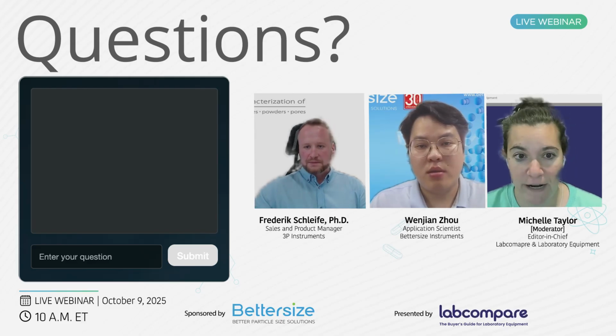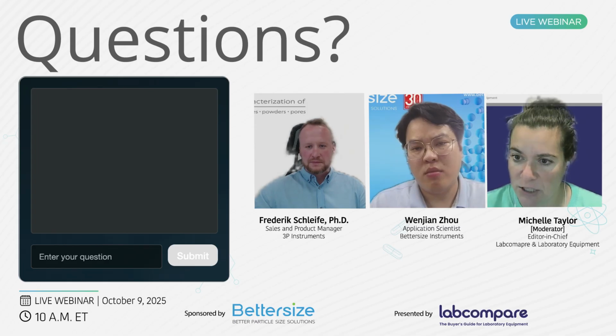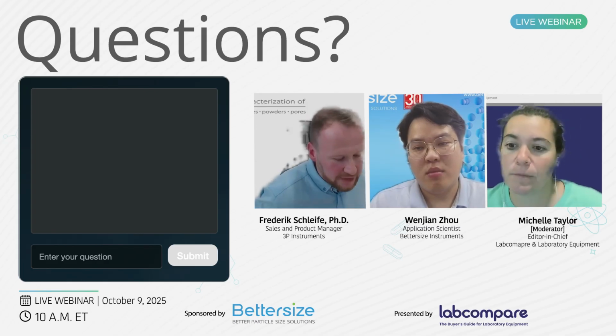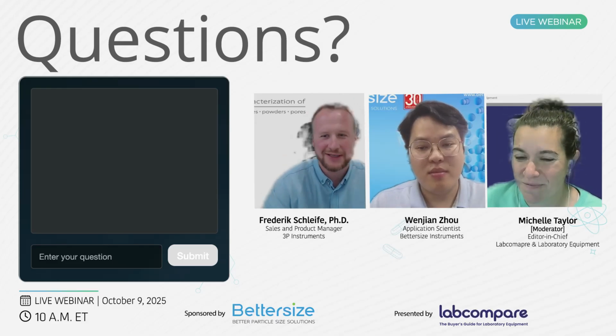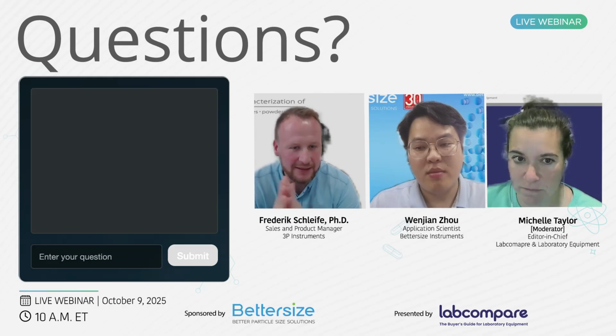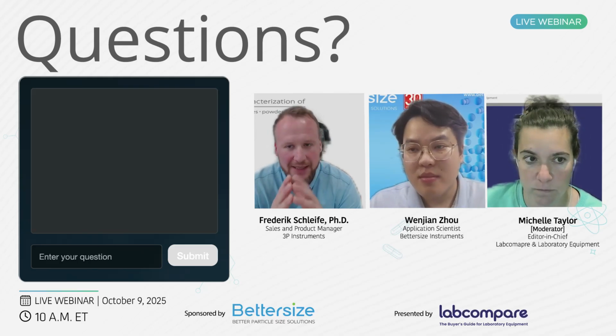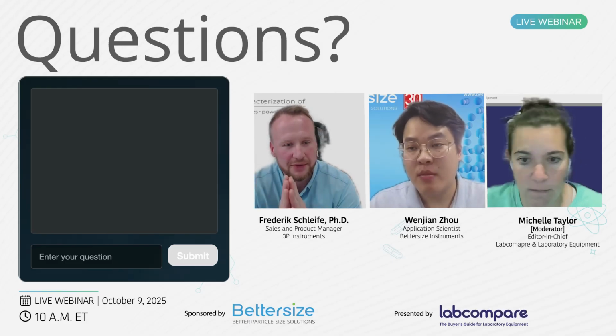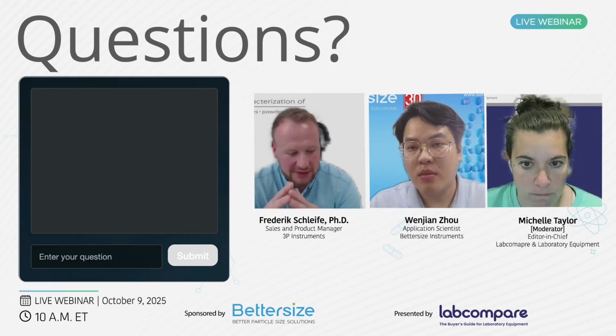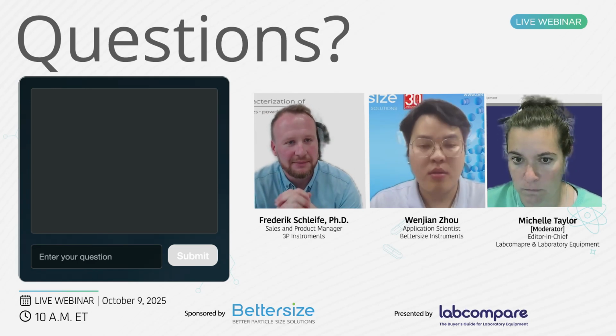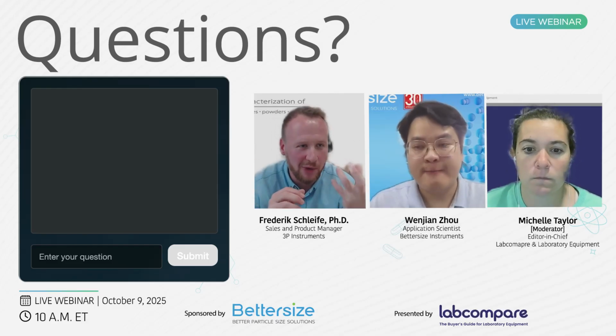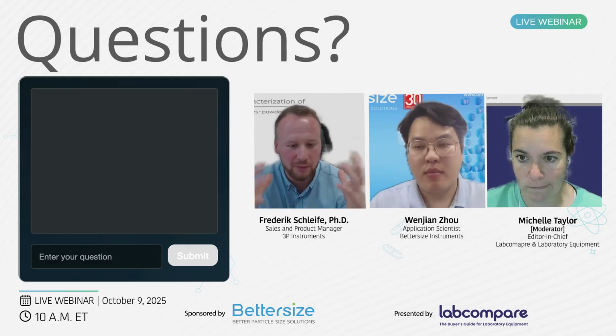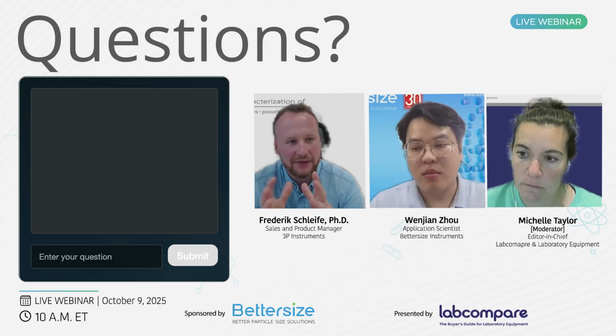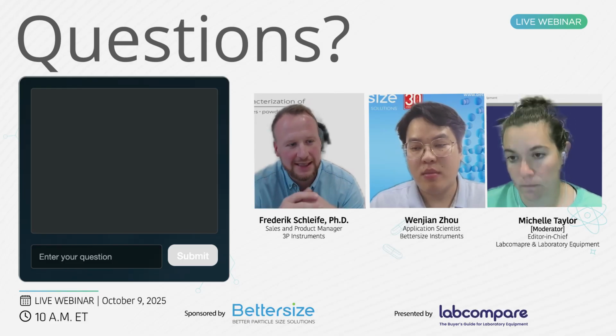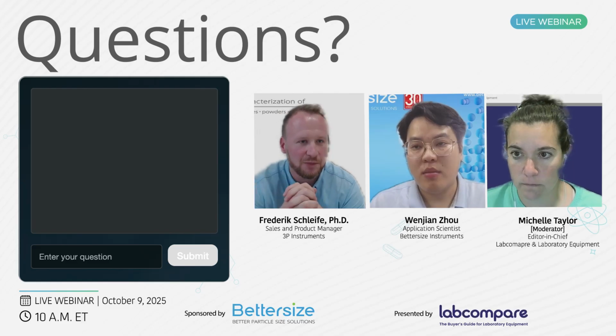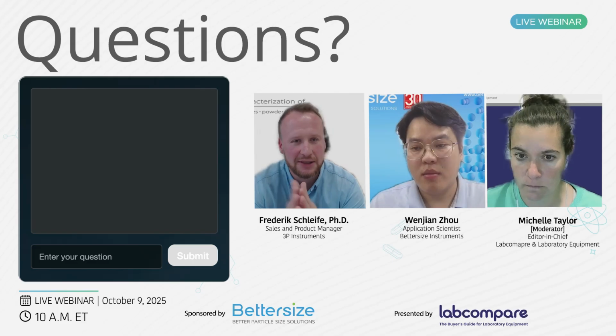All right, last one for you, Freddie. What are the limits of granulometry laser? The limits of laser diffraction in general, I think, is how I would interpret the question. I think Wenjian tried to show this also a bit. Basically, in laser diffraction, we get volume-based distribution curves. The benefit of laser diffraction is clear: it starts in the nano range, going up to the millimeter range. But especially if you have broad distributions, the small particles are in terms of number always way more represented than the big ones. So laser diffraction in general struggles a bit with oversized analysis, to identify the small number of large particles. It might lead you to some troubles, especially in ceramics, but also in other fields.